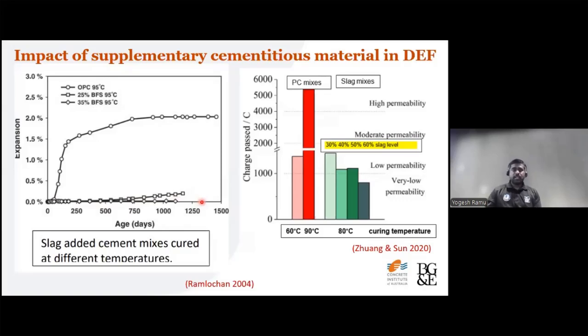And also, like I already mentioned, it leads to a lot of pore size refinement. On the right side, you can see the RCPT, rapid chloride penetrability test results, where with increased slag replacement level, despite curing at 80 degrees Celsius, there is very low charge passed, which means very low permeability in the concrete samples.